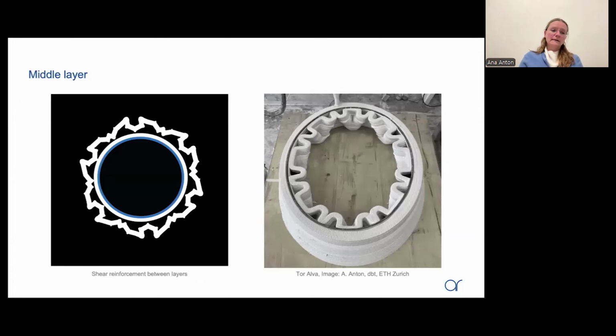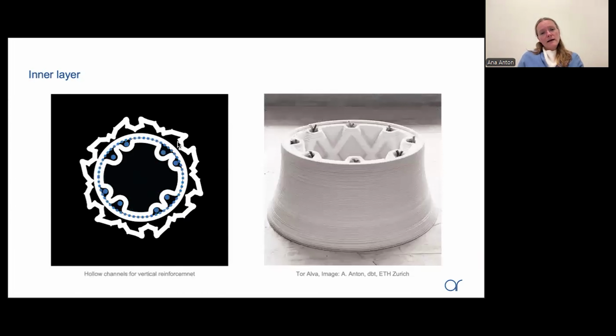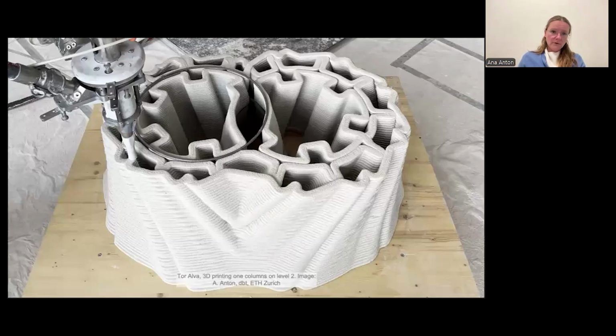Because we had worries about the durability in combination with the 3D printed material, and we operated on such a tight timeline that we didn't have time to see the long-term behavior and the corrosion rate of regular steel in 3D printed elements. So we opted for stainless steel reinforcement, and the innermost channels create a space for the main reinforcement, the vertical reinforcement, which is later on grouted to create the structurally stable component.